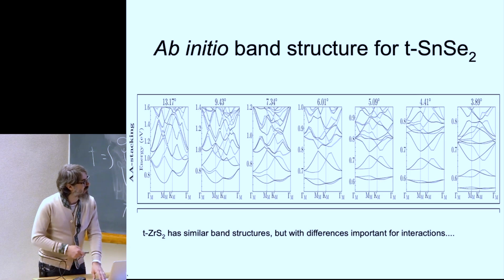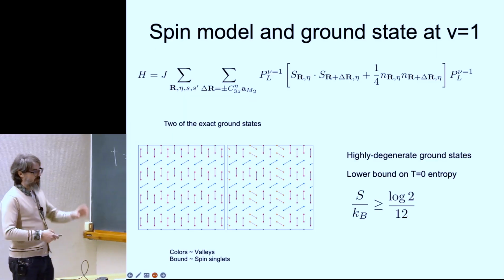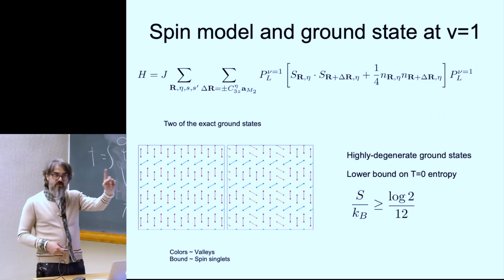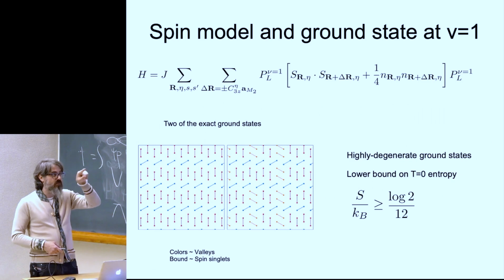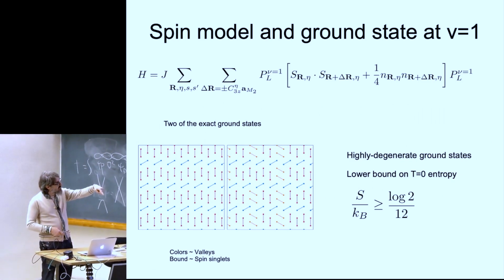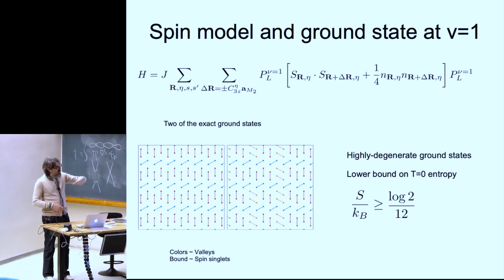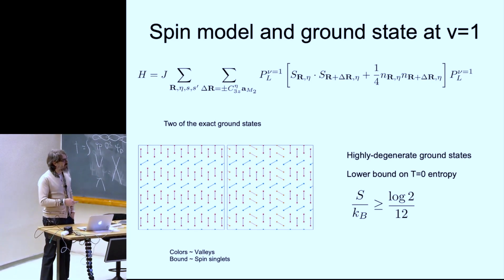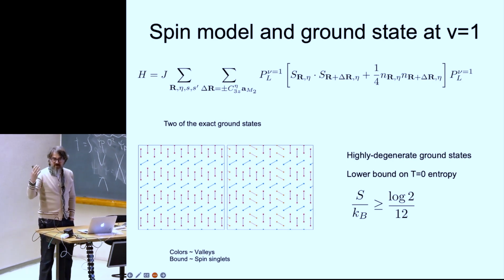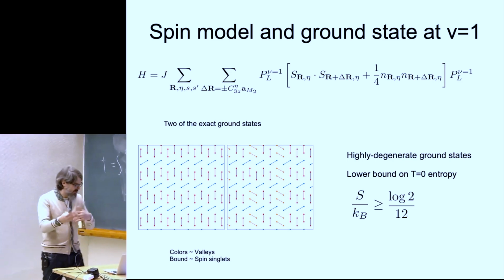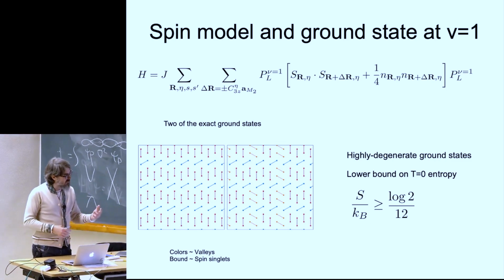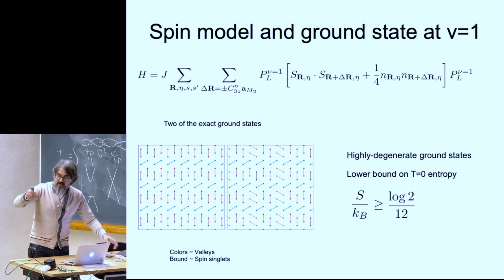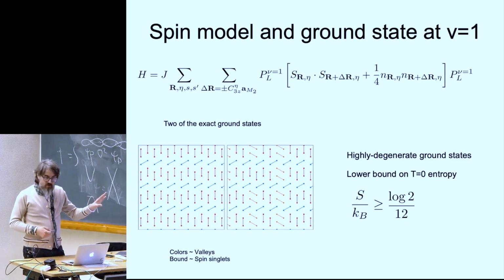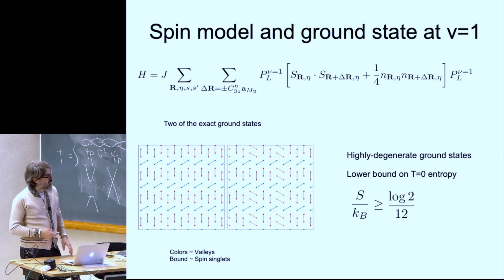That's not true, because of the way this M point twisting works: you have directionality in different directions for different M values. You have 3 M points. So you have directionality in one direction for one value due to some non-crystalline symmetry that comes out. In the other value, you have directionality in the other direction. So then, when you go below the charge gap, you basically have a t-J model. So this is a quantum simulator for one-dimensional spin liquids, because the t-J model in one dimension is a spin liquid. Of course, asking how this gaplessness breaks down by adding longer range hoppings, which are bound to be very small here, is a new question that people are working on. But I wanted to point out that you can get simulators for spin liquids here.